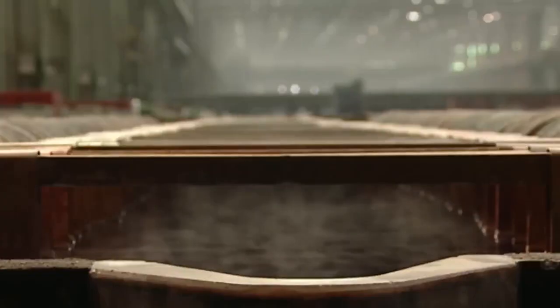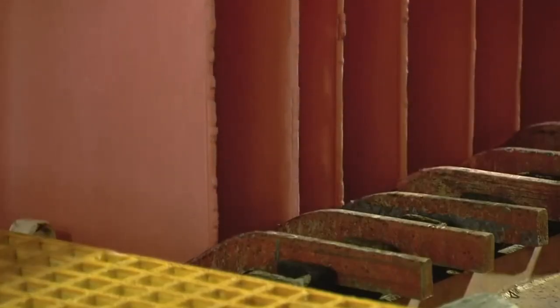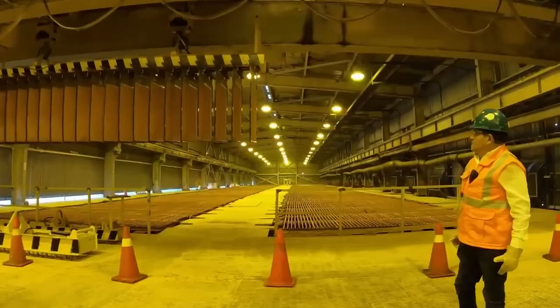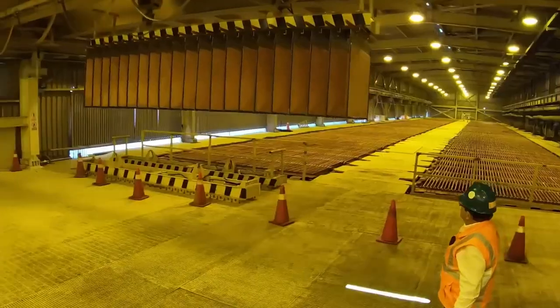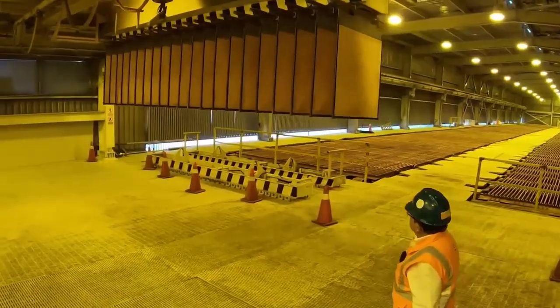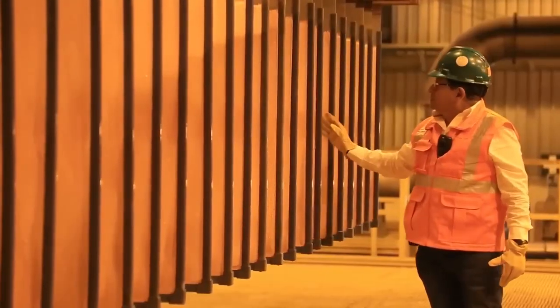The solution is transferred to a series of tanks with thin copper plates called cathodes. An electric current is applied, and copper ions begin to deposit onto the plates. In just 10 days, each plate reaches a thickness of 2.5 centimeters and a weight of about 125 kilos. The purity reaches 99.99%, which is essential if the copper is used to make electrical products.